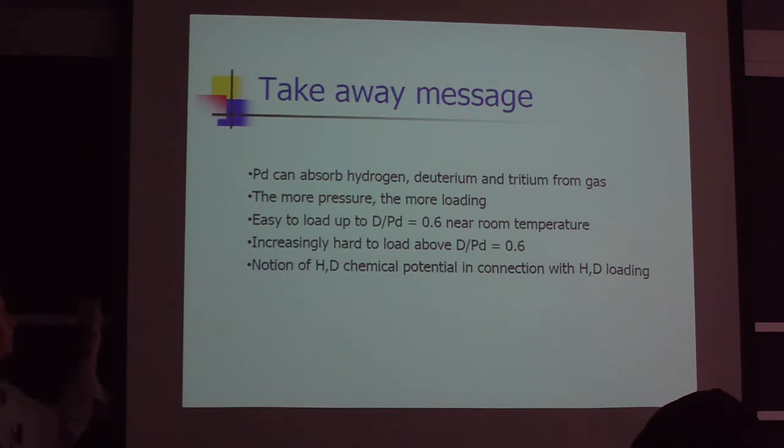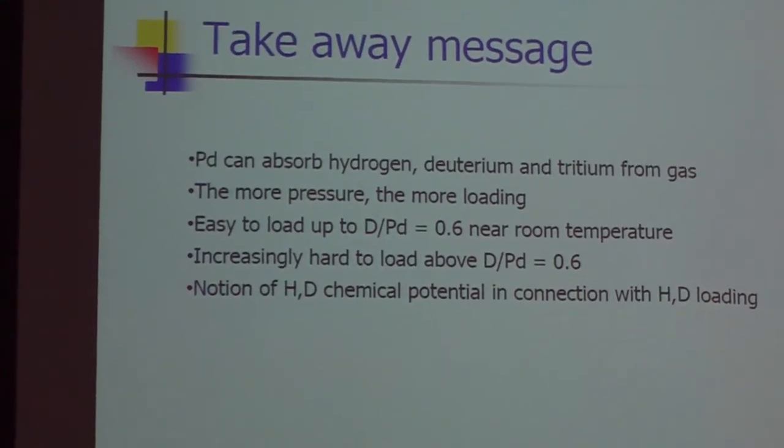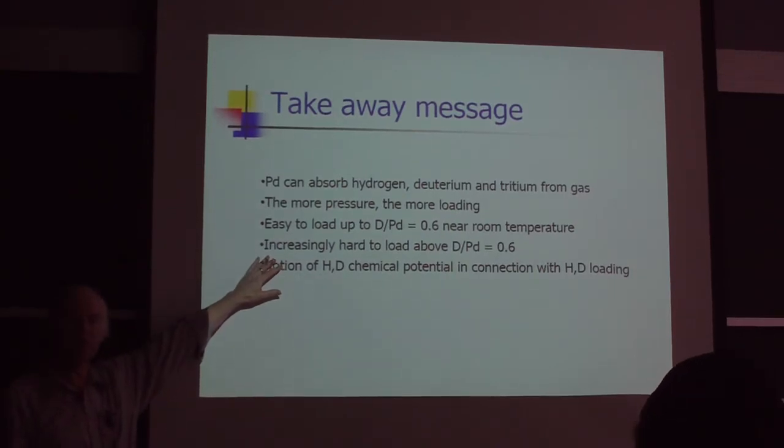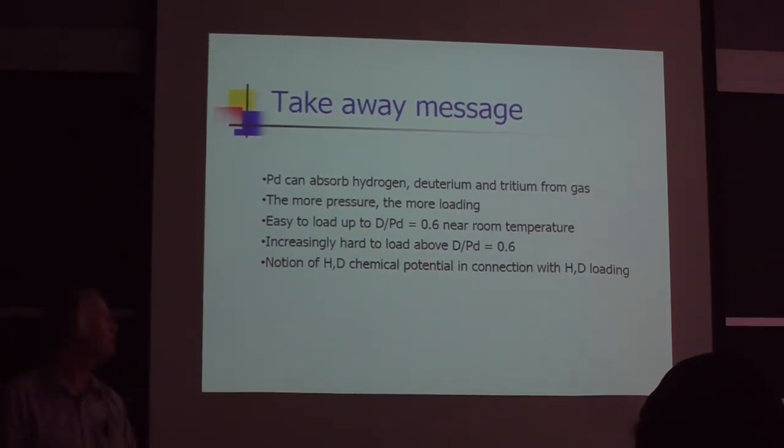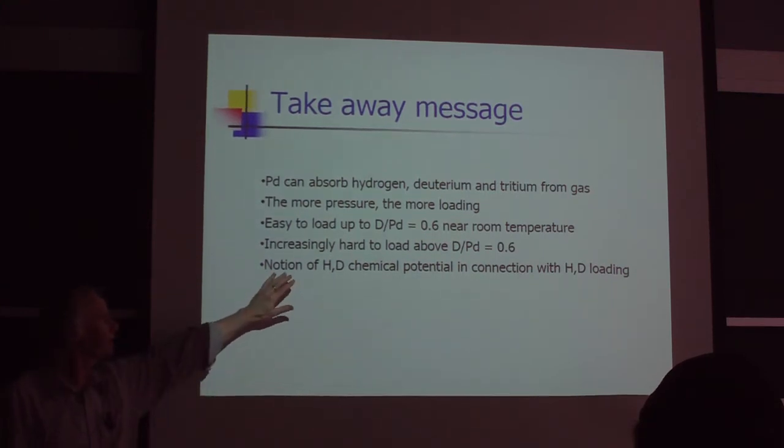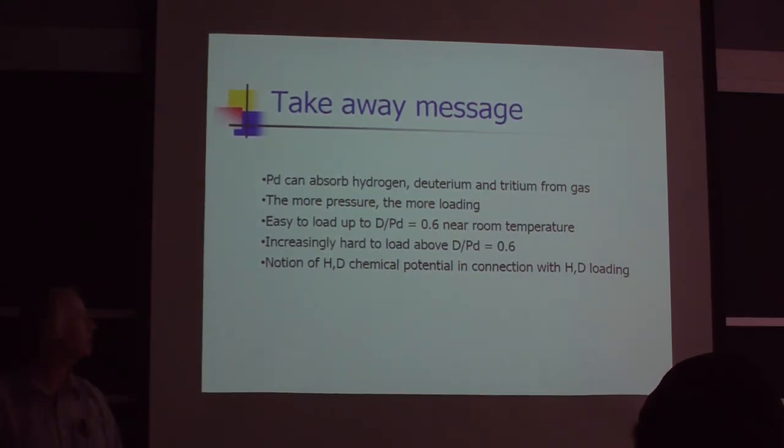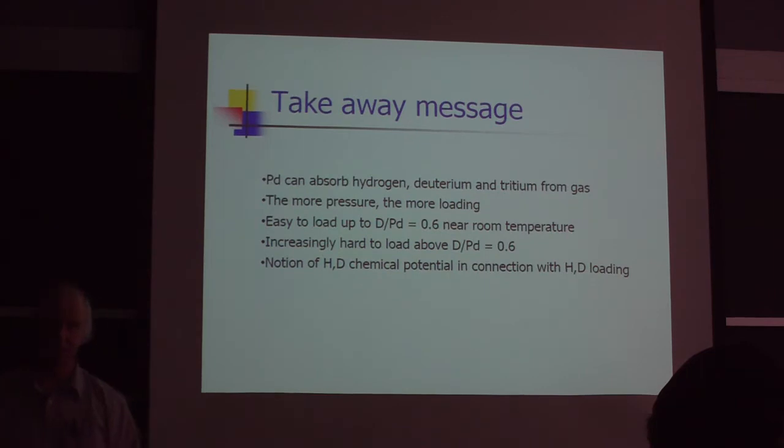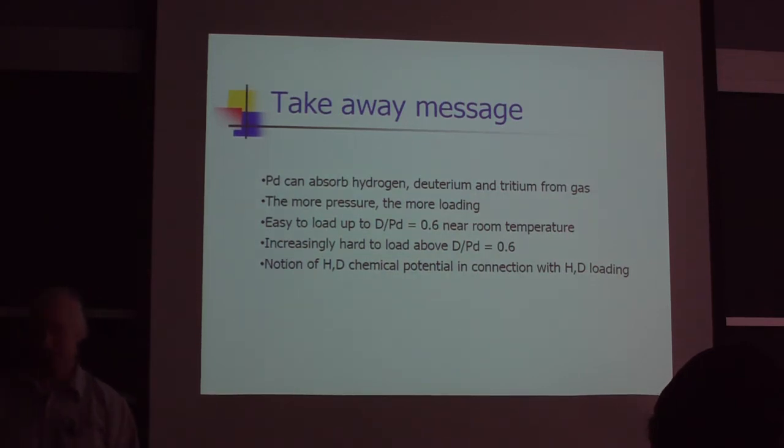The takeaway message: palladium can absorb hydrogen from gas, more pressure gives more loading. It's sort of easy to load the palladium to loading of 0.6 at room temperature. Once you go above the miscibility gap at room temperature, it becomes increasingly difficult to do the loading. And we've introduced now the notion of a chemical potential associated with hydrogen and deuterium loading of the palladium, and the same idea applies to loading.